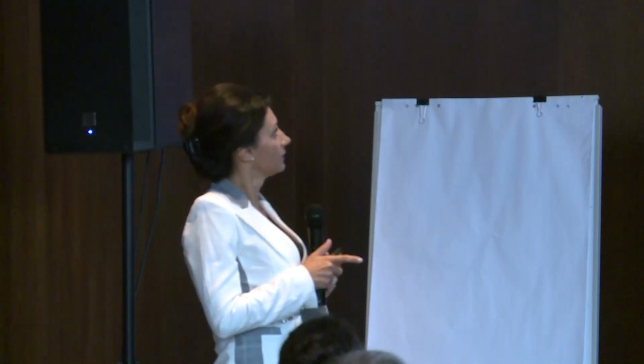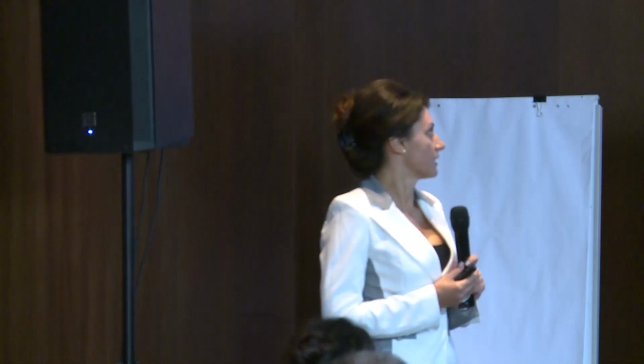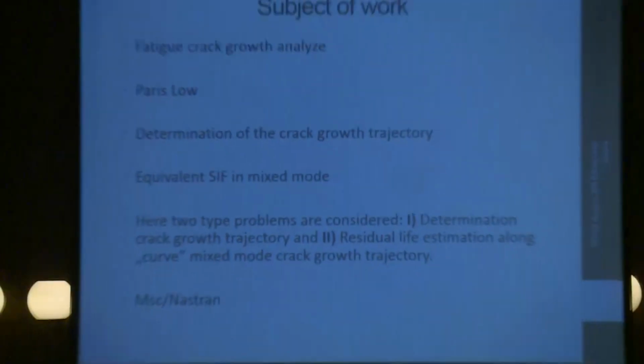The subject of this work is fatigue crack growth analysis using different models, the Paris law and the strain energy density method, to analyze the crack growth, and numerical simulation for determination of stress intensity factors for mode 1 and mode 2. We calculated the equivalent stress intensity factor in mixed modes and the angle of crack growth for each increment of crack length. Two types of problems are considered in this work: determination of crack growth trajectory and residual life estimation along the curved mixed mode path. For this purpose, we used the software package Nastran to determine the stress intensity factor.